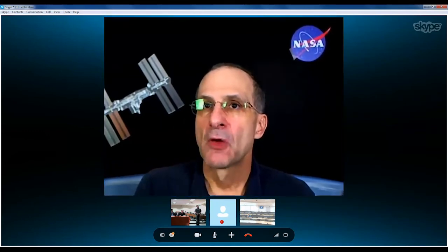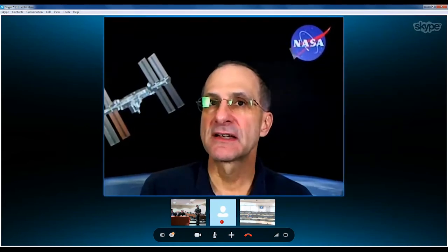and then applying the heat, maybe you would need to have a material that would glassify at a much lower temperature. And what I'm thinking is you might just want to use some concoction of the silicon-based oil without any added frit, because if you've got a little narrow crack, the oil could creep into the crack, and then you could decompose the oil and make a glass bond. So that would be the crack phase, whereas you might have a big chip or a divot in a windshield. I'm trying to think what would be good to fill that up. Anyway, interesting idea. I hadn't thought about that. You need to run with that, and maybe you could make a different formulation of this that could be used as a windshield repair. Then you could stand at the street corners and put a sign up that says free windshield repair.